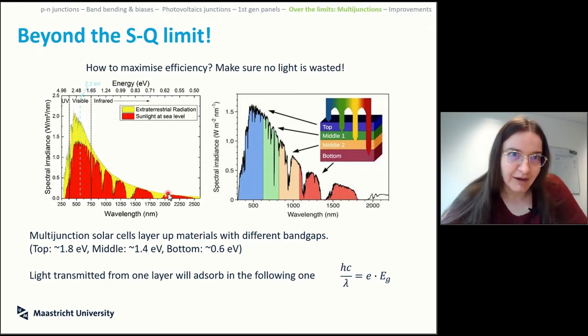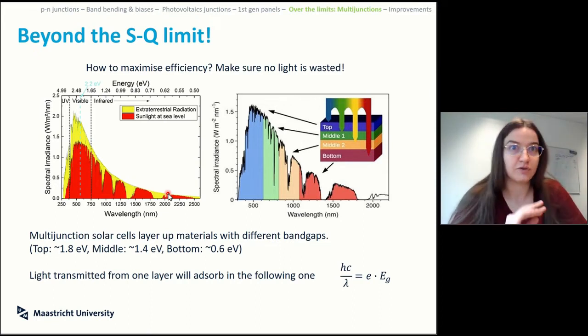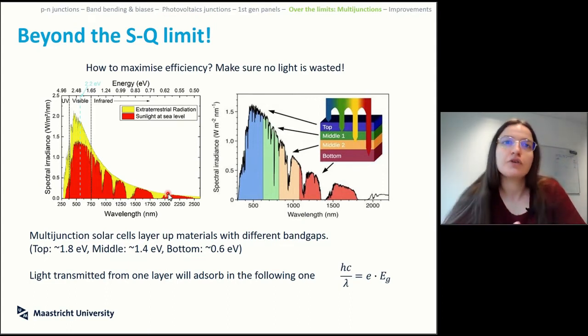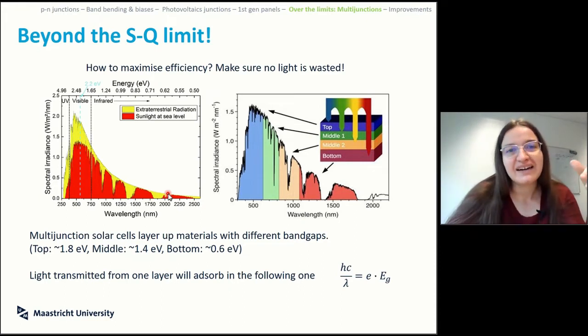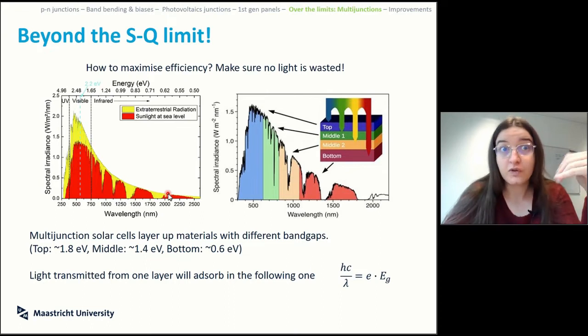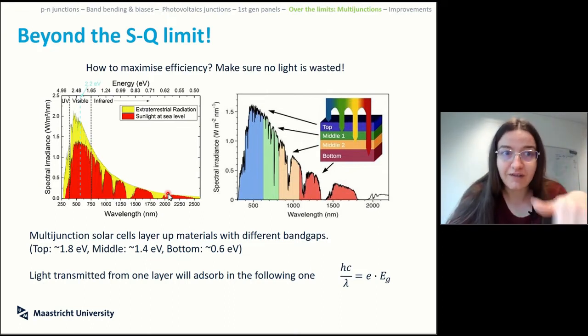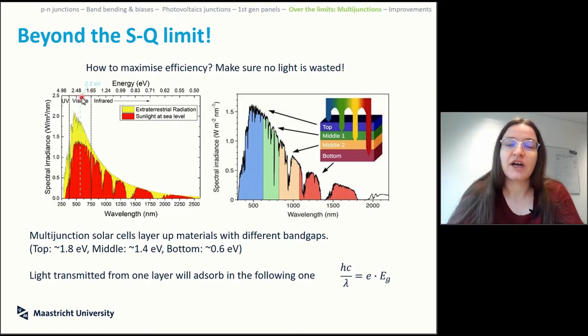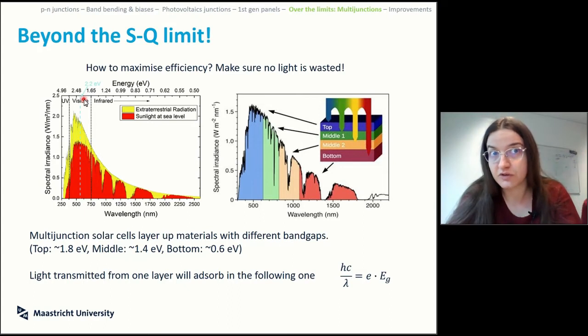Now, the issue is that, as we were talking about, the Shockley-Queisser limit comes up from the fact that you have a single junction cell. And as we were saying, the optimal working of the junction is at the right energy to bridge the gap. So ideally a single energy. You could deviate a bit because you can live with something slightly higher that will result in a slight loss. You know that if it's lower, it's not going to be absorbed. So if you have a band gap of 1.6 electron volt, for instance, and you shine 1.7, 1.8, 2, you will still absorb the photon with lower efficiency because you will lose something as heat. But if you shine 1.5, that thing is lost.